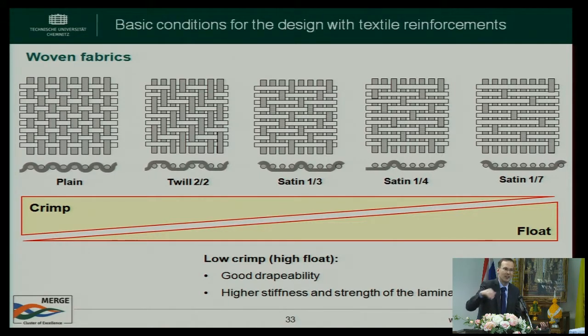You are going up and down, and always remember on the basics, fiber reinforcement effect is only in fiber direction. Now, as you can see here the fiber direction is in this direction, going around, your fiber direction goes there, going down. So you don't have such an efficient using of the fibers, because your fiber direction is not only in plane, but it also goes in thickness. So woven fabrics are easy to handle, but because of the crimp, your stiffness of the laminate is not so good as if you have unidirectional fibers.